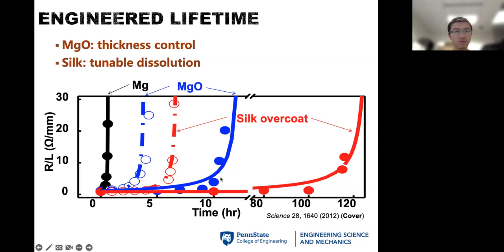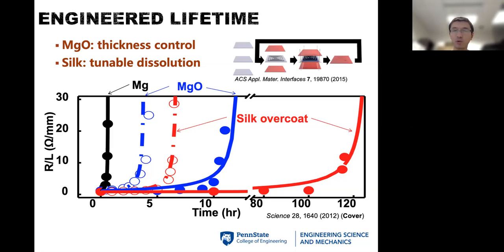But of course, that's not sufficient for many applications. So we can further engineer an overcoat from silk. It's pretty much like a rain jacket that you put onto the device, and that will protect the device for an even longer time, for example 5 days, which is probably sufficient for many surgical operations while the patient recovers. And if one layer is not enough, you can do that over multiple cycles and achieve a much longer period of time.